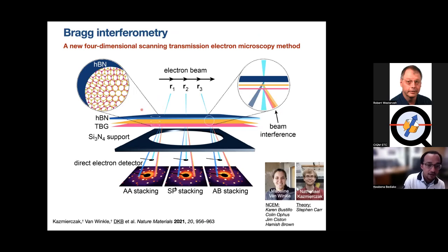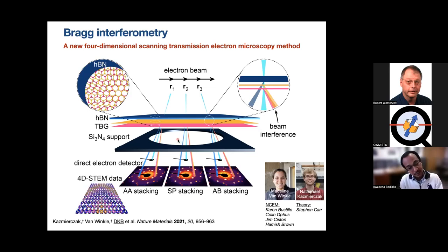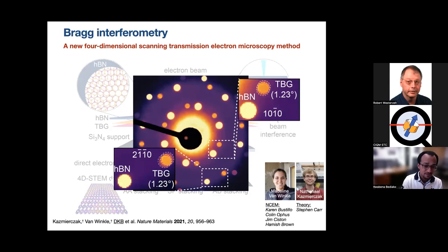And so it's called four-dimensional STEM, simply because we acquire this two-dimensional diffraction pattern at each two-dimensional position, scanning over two dimensions in real space. And so our data set then is this 4D STEM stack of diffraction data. Okay, now what we initially set out to do was to use traditional 4D STEM strain mapping. 4D STEM has been around for a few years.